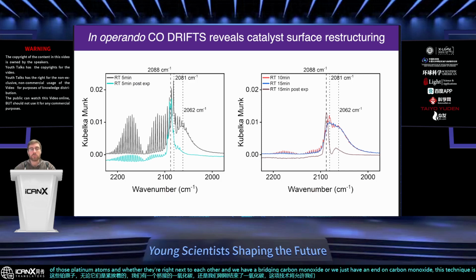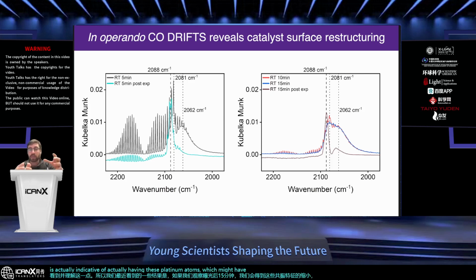And so some of the results that we've seen most recently is that if we look at 15 minutes post-exposure, we get this narrowing of these resonance features, which is indicative of these platinum atoms, which might have been clumped up together upon initial synthesis, actually spreading out across the surface of the gold and becoming more localized and isolated overall in those systems.